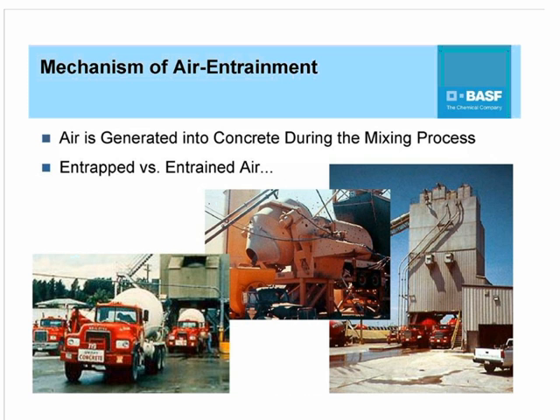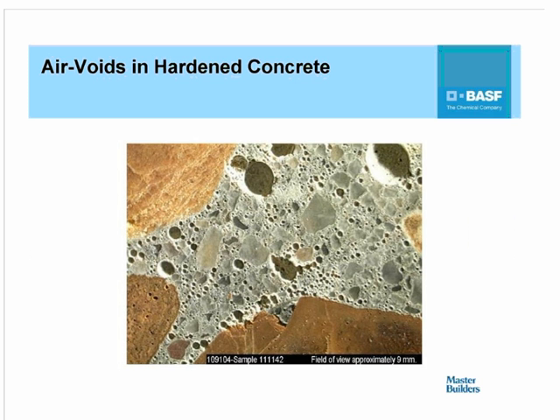provide. Now, the air, as I indicated, is basically generated into the concrete during the mixing process when the air entraining admixtures are used. And they form air bubbles that are spherical in nature, as opposed to the irregularly shaped, larger entrapped air voids that really do not provide any benefit when it comes to cyclic freezing and thawing. And in hardened concrete, this is what the air bubbles look like.